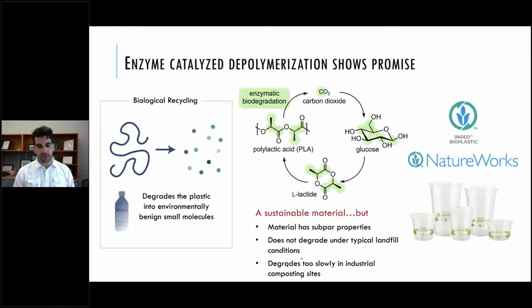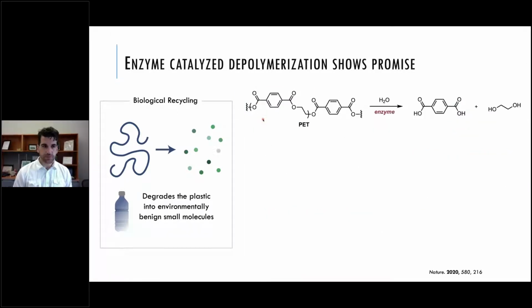And that is the same even in industrial composting sites. So if you can divert this waste to industrial composting sites, that's great. But actually it degrades too slow in industrial composting sites to really be economically valuable. So ideally, right, I think there's one way to biologically recycle polymers: create a polymer that can be recycled by biology. But ideally, we create a polymer that has better properties and composts a bit faster. But still, PLA is a great material. I do really like it.